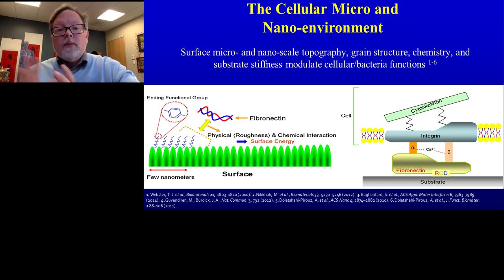So if you know that a certain protein promotes bone growth, then figure out what the energy of that protein is and make your surface match that energy. Similarly for bacteria, if you know that mucin, which is a protein in your saliva, can reduce bacteria growth, then figure out what the energy of mucin is, make your surface through nano features match that energy, and then you can increase the adsorption of mucin, which will inhibit bacteria from attaching. And again, this is all without antibiotics, all without drugs. It's changing the surface to give you the energy you need to promote the adsorption of proteins that these cells depend on to attach or not.